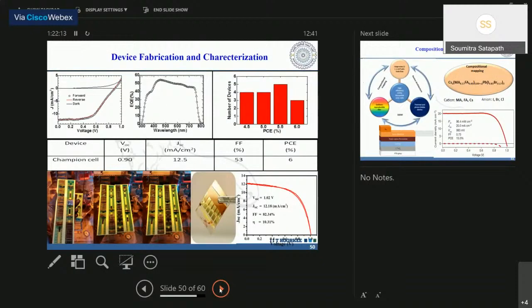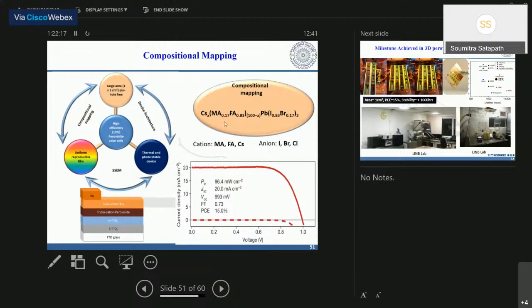In compositional engineering, instead of one particular organic cation, MA, we use three different cations with a particular stoichiometry, which has been optimized over the years. For example, we use methylammonium, we use formamidinium, and we have also used cesium. So organic and inorganic cations both. And instead of iodine alone, we have used a bromine-iodine mixture. This process is called compositional engineering.